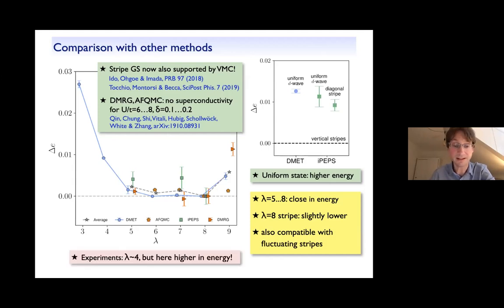Okay, so one of the issues with this data is that the typical stripe period that is observed in experiments is not period 8, but period 4. And the period 4 stripe here is clearly higher in energy. But of course, it might well be that once we move to a more realistic model of the cuprates, these energies might shift, so that the period 4 stripe could get favored.